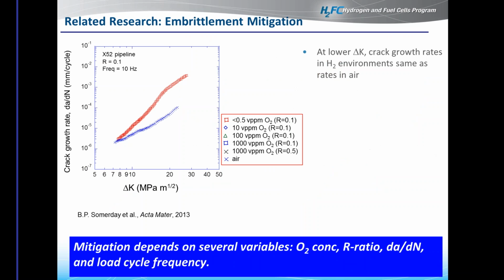And so that's exactly what we did. We took an X52 pipeline. We did our typical tests. So we performed fatigue crack growth tests in air, which are represented by the blue X's here. And we performed them in high purity hydrogen, and that is the red curve here. And you see hydrogen accelerated fatigue crack growth occurring at a low delta K and at a low da/dN.